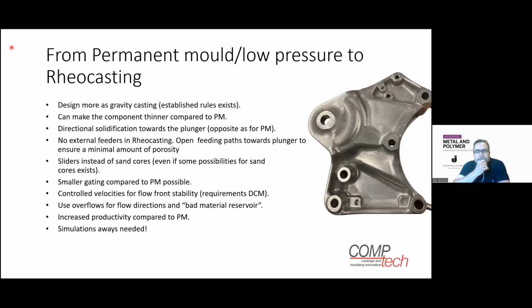And then if we look at the other type of castings, where we come in from the more permanent mold, thick wall castings, the design here is different compared to thin wall, because we only have one source of pressure, which is the plunger, and we need to see that the part can solidify towards the plunger, so we have more pressure roads open inside the casting, if I may say. So you need to think a little bit more pressure with Rheocasting compared to perhaps speed as you normally think in liquid casting. So we need to ensure that we get the right solidification path towards the plunger.